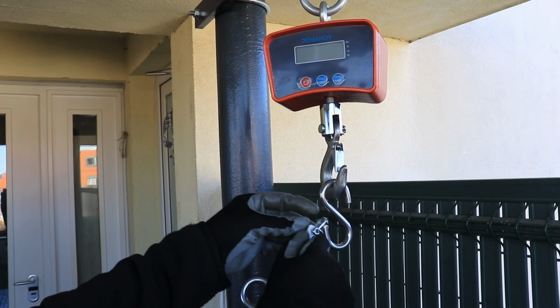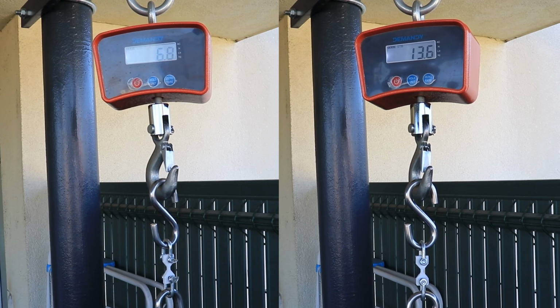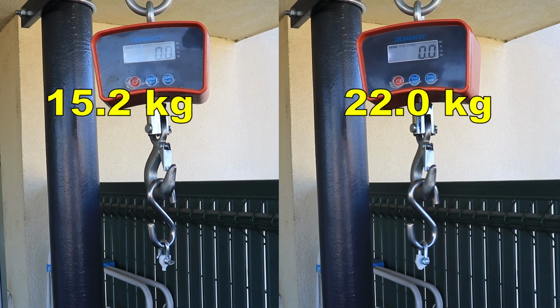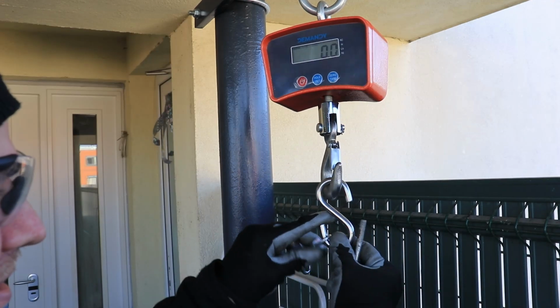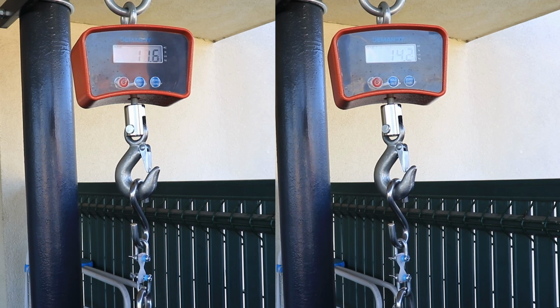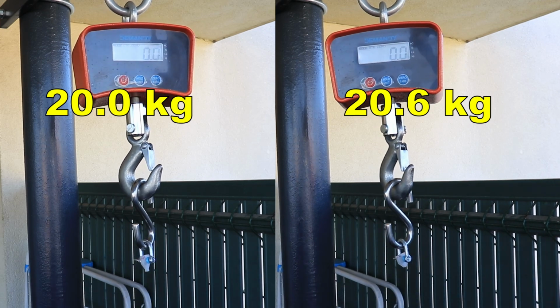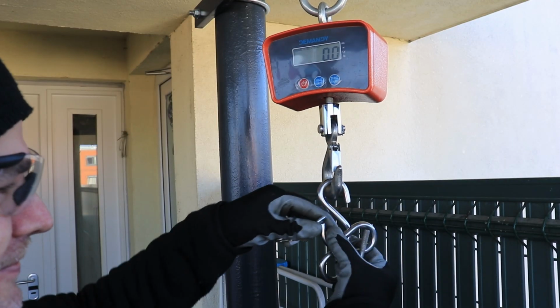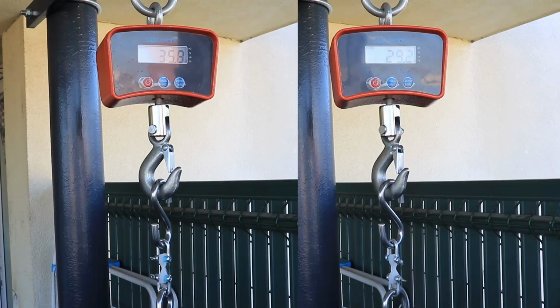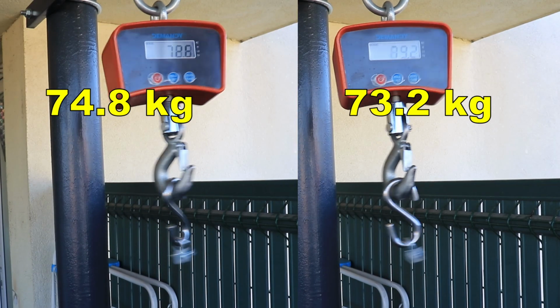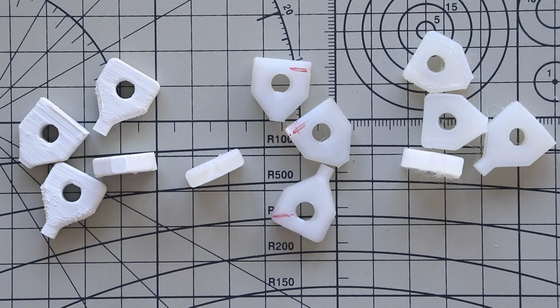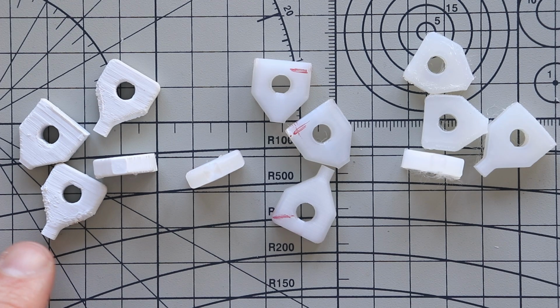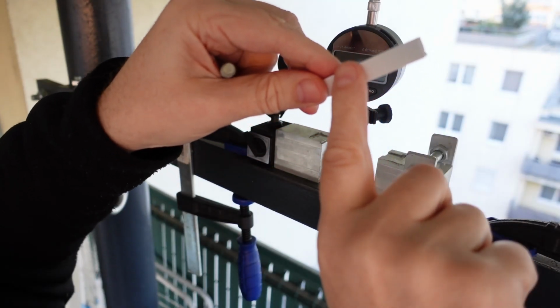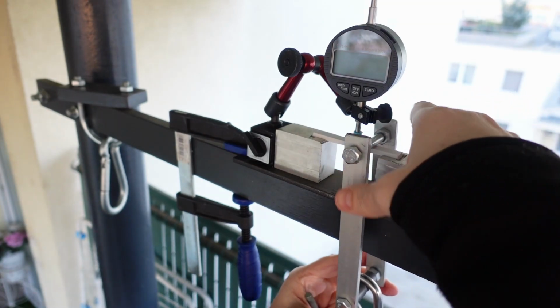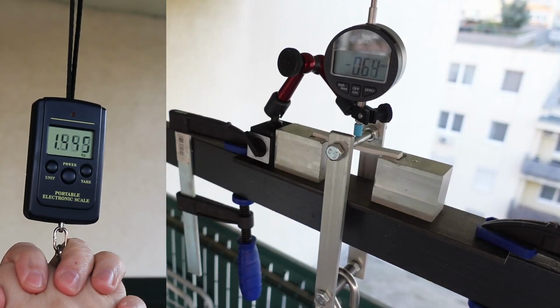The next experiment is the layer adhesion test, and again the smaller cross-section area is 4 by 4 millimeters, and I'm starting with ABS. Then the next is the polycarbonate. I was expecting a little bit bigger layer adhesion here. And then the nylon, and here I was really surprised. It was extremely strong, it was very hard to break it with my hand. And this is how they broke, exactly on those smaller cross-section areas. This is ABS, polycarbonate and nylon.